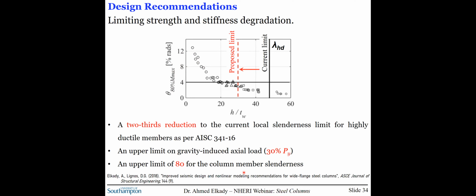So the recommendations included a refined upper limit for the column local slenderness, and essentially we proposed to push the current limit by 2/3 to the left, as you see here. This is the limit for highly ductile members, noted as lambda_hd. At the same time, we proposed an upper limit for the gravity-induced axial load of 30% Py, and an upper limit for the global member slenderness of 80. Again, these are all to achieve the target performance that I showed earlier. But given that you have the data, you can target any performance criteria that you would like and see which cross sections or limits on the loading you need to induce.